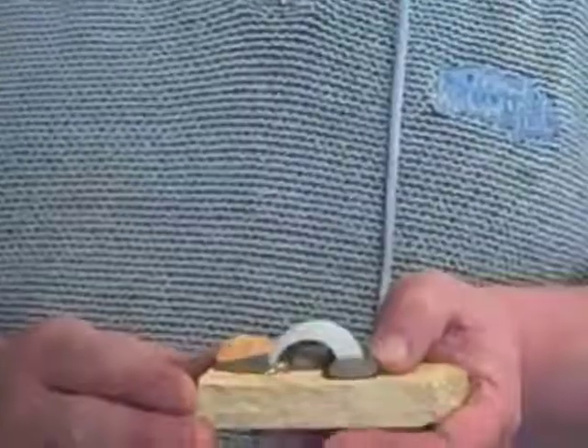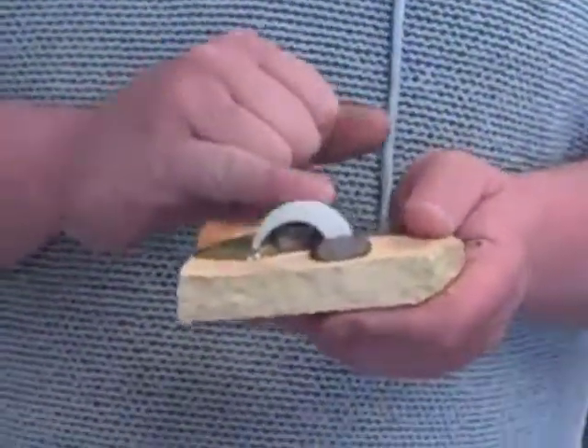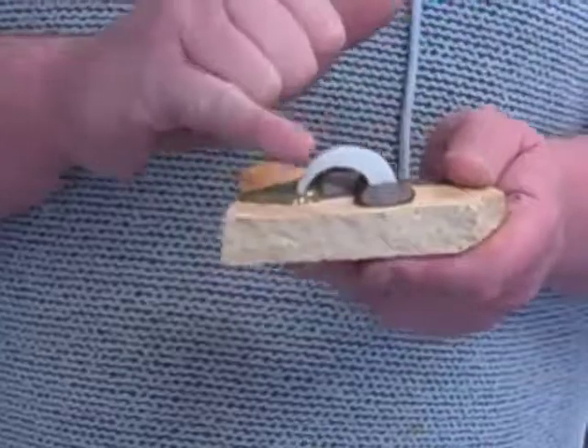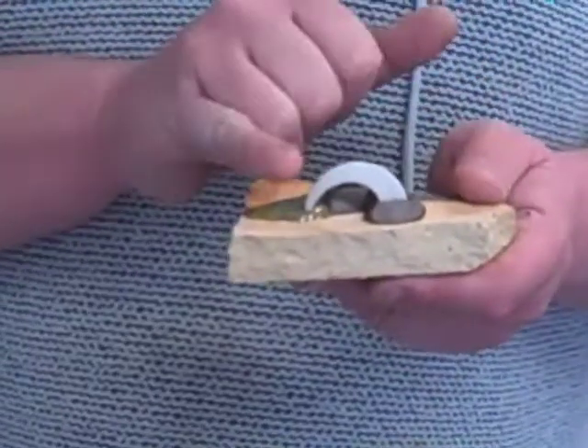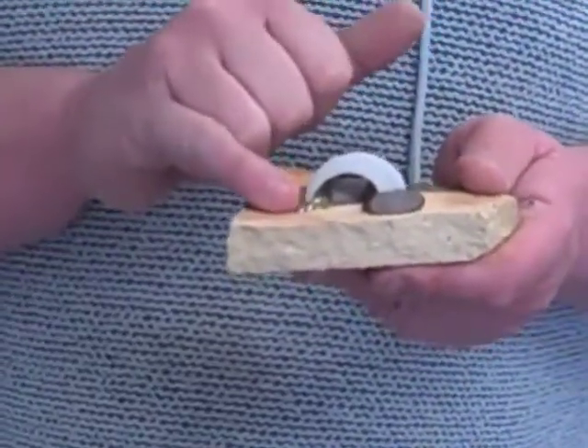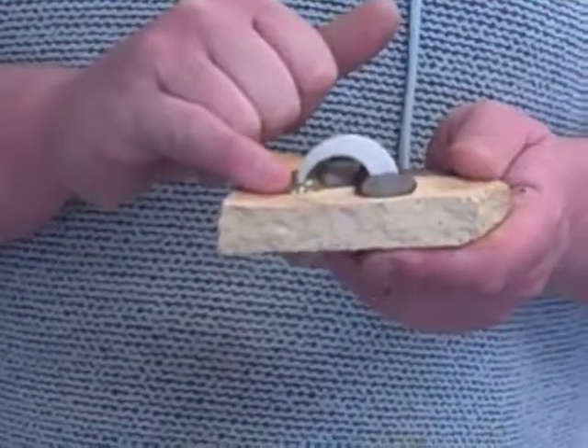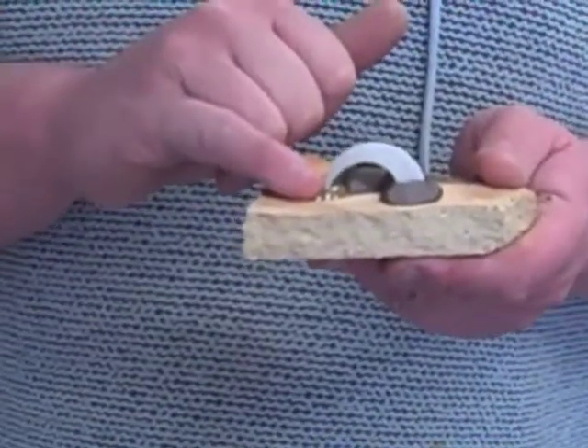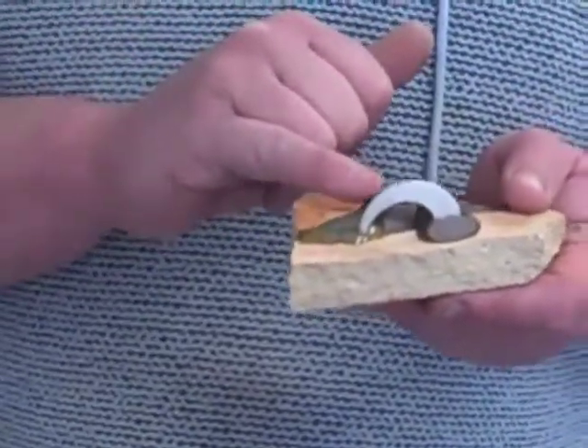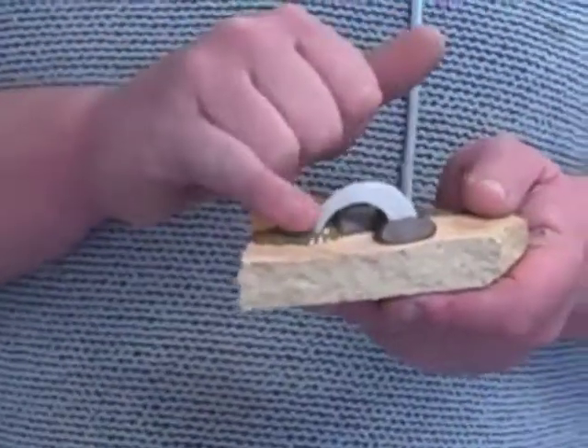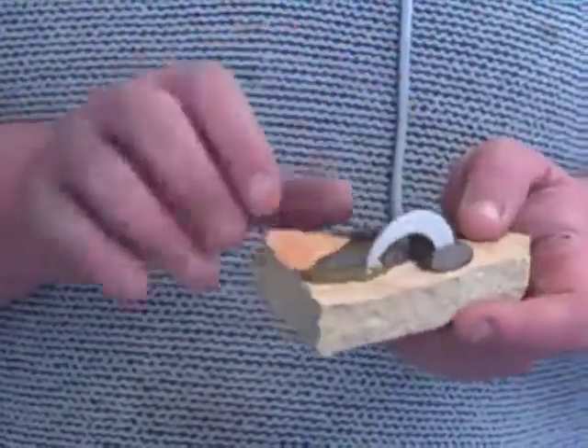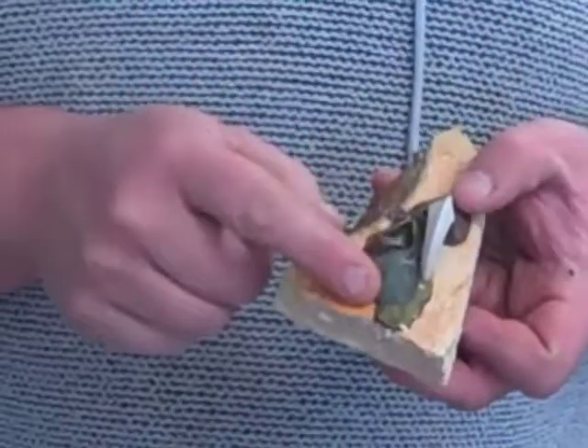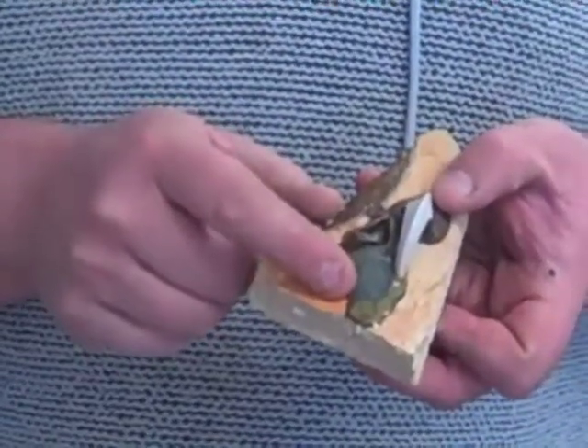It's 48 hours since we fired the kiln, and we've unpacked it now. I was telling you earlier about the cone that I put into the kiln. Well, this is the cone that's come out of the kiln, which is bent. It was upright and it's bent over, and where it's touched the kiln shelf is exactly 1280 degrees. And the first cone is designed to melt tip to base at 1000 degrees. But you can see that there's not much left of that cone because it's gone up so hot.